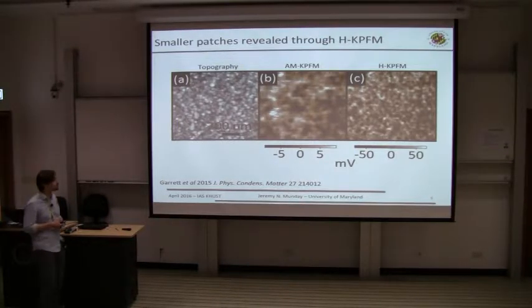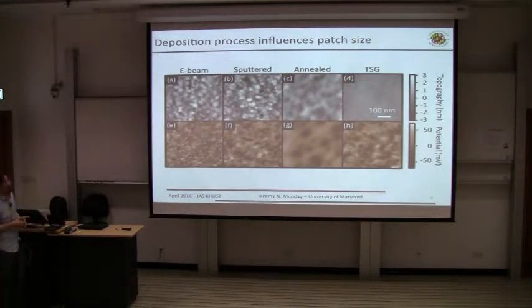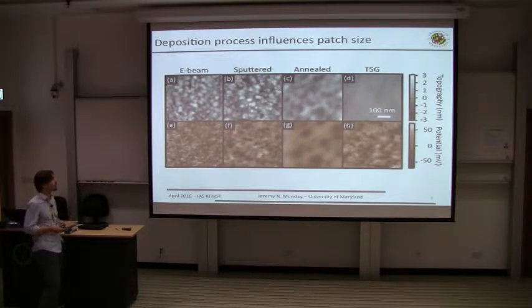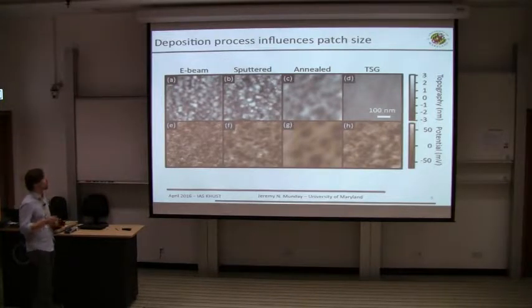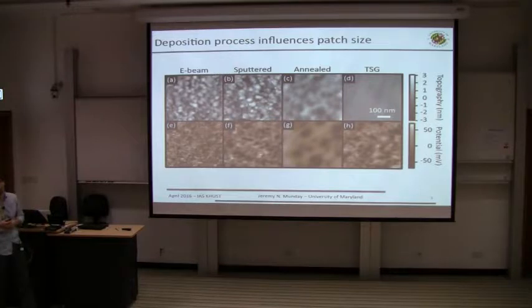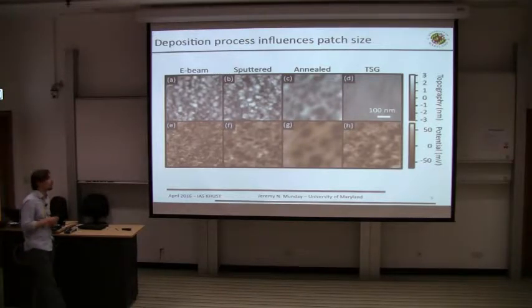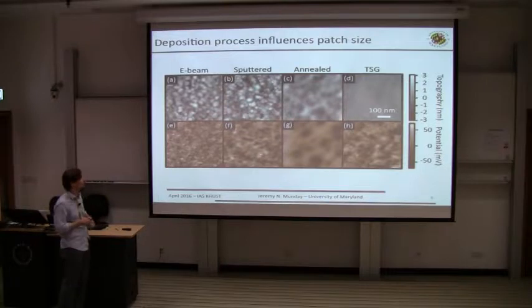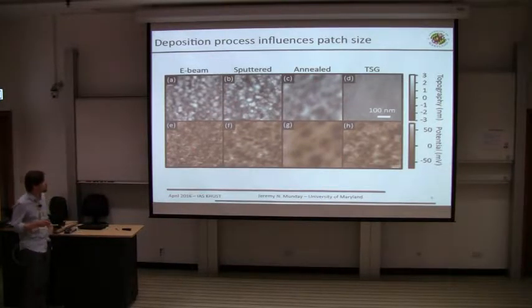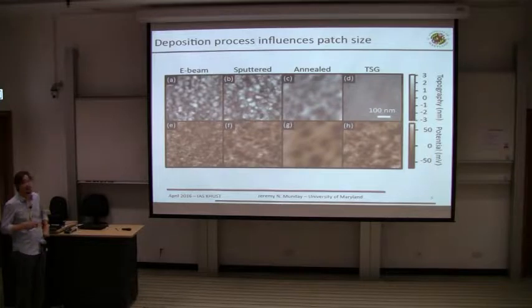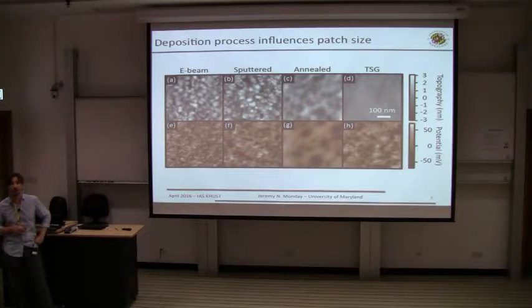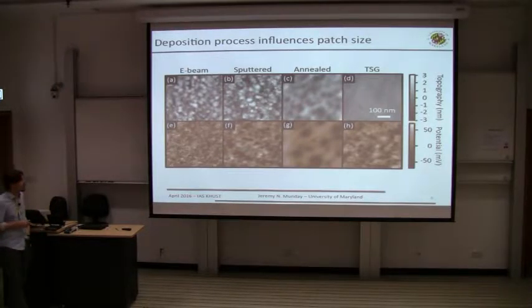So we then wanted to look at different samples to see if we could find which samples would have a smaller patch potential effect for doing these types of experiments. So we looked at E-beam deposited gold, sputtered and annealed, and also template stripped gold. This is a type of process that allows usually very smooth gold samples. And you can see, interestingly, that all of these give patches that are about on the same order of magnitude for their overall value, but the spatial variation is very different. And the spatial variation is important when it comes to determining the effect of patch potentials on any sort of force measurement.